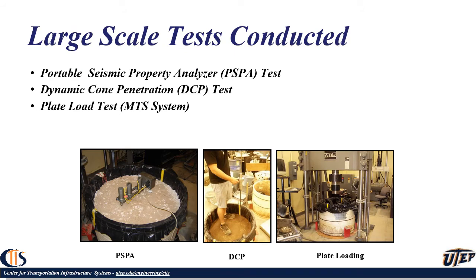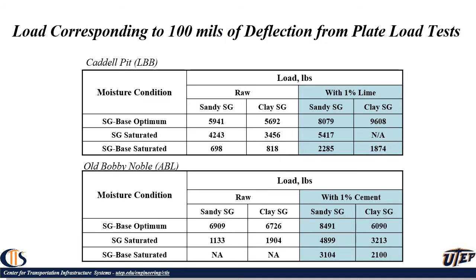The next step, before putting it into the field, was to test it and make sure that the material is working. So we made these 1 meter scale specimens, putting them under an MTS dynamic loading system, and we started applying loads on them. And we used seismic testing and dynamic cone penetration to get the strength and the modulus of the layer, and then we performed plate load tests under the MTS. And this is some of the information that you see.